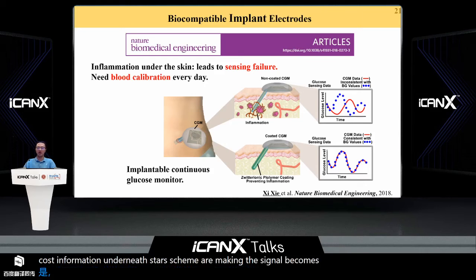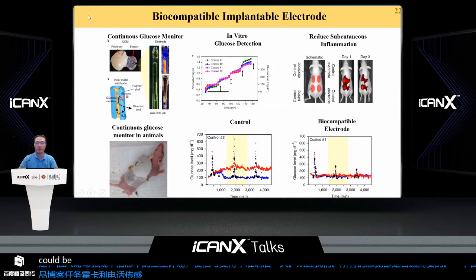However, an implanted glucose electrode could easily cause inflammation underneath the skin, making the signal inaccurate right after one day. For commercial sensors, it generally requires the patient to do blood tests to calibrate the sensor every day. So here, I developed a zwitterionic polymer that could be coated on the glucose electrode to improve its biocompatibility. This coating could greatly reduce the non-specific adhesion of proteins and hence inhibit the occurrence of inflammation.